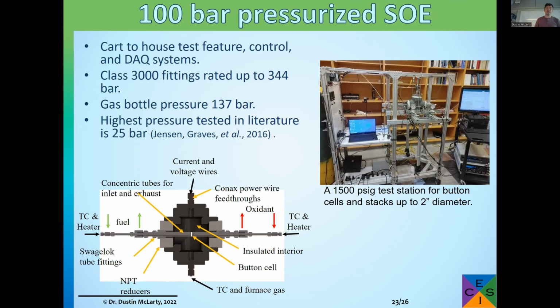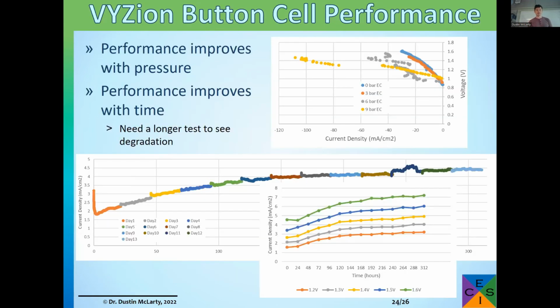The rig itself is rated for 3,000 psi, so we could go to 200 atmospheres eventually, but the gas bottles we get supplied are around 137 atmospheres, so we really only get about a quarter of the bottle if we're supplying it at 100 atmospheres. So eventually we'll take this even higher pressure, but this has been an enormous challenge to build. But it's very exciting because we're getting some fantastic results that the world's never seen before. So if you have any interest in collaborating on this, feel free to reach out.